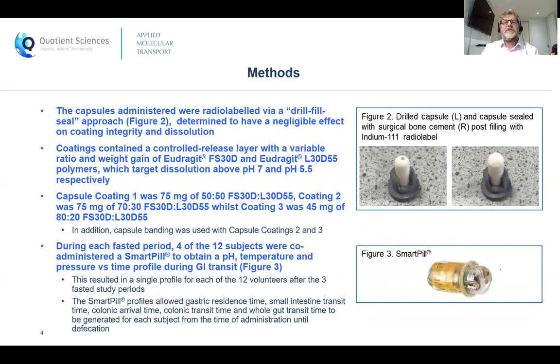The capsules dosed in the study were radio-labeled by drilling a small hole in the coated capsule shell, filling with a short half-life radio-labeled indium-111, before sealing the hole with a surgical bone cement. A pre-dose formulation development package was completed to ensure there were no significant impact on the test product coating integrity or dissolution performance. The 3 test capsule coating systems comprised of different ratios and coating weight gains for mixtures of Eudragit FS30D and L30D55 polymers, which dissolve above pH 7 and pH 5.5 respectively.